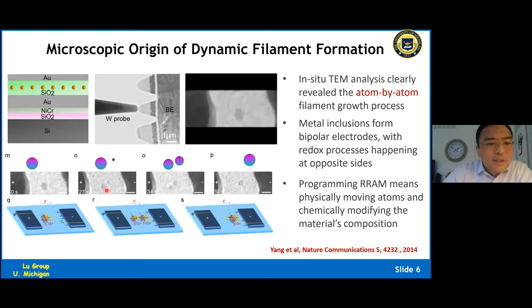Suppose I stopped the video here, then you can see that the original particle starts to shrink, and it doesn't shrink uniformly. It starts to shrink from the anode side. So it starts to lose silver atoms from this side, because this is the anode side, it's positive charge. So as I explained earlier, on this side you start to lose silver atoms in the form of silver ions. And silver ions will migrate in the direction of the electric field. In this case, it will migrate a very small distance, then be reduced, and it captures electrons inside the film and will be reduced and form this new cluster.